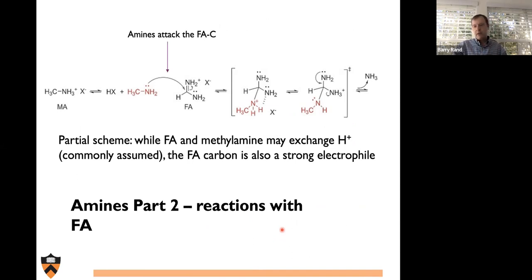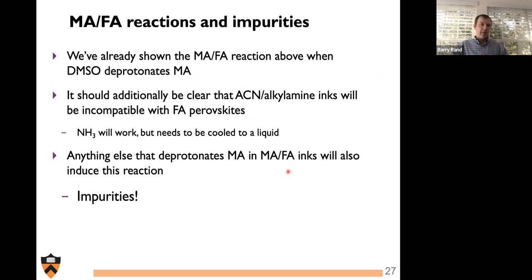Now, with a little more notice to what can occur in formamidinium-based inks, it turns out that an amine will undergo an addition-elimination reaction with formamidinium spontaneously, whereby the lone pair of nitrogen will attack the carbon in formamidinium and lead to the addition of the methyl group from, in this case, methylamine, to make this MFA system, and you'll eliminate and produce some byproduct ammonia in its place. We've already shown this MA-FA reaction above in the case where DMSO deprotonates MA. That's one way you can have methylamine around.